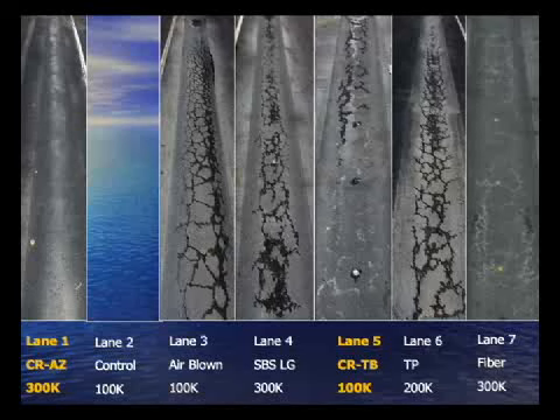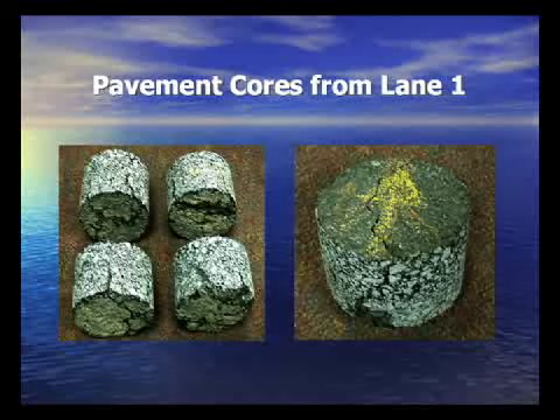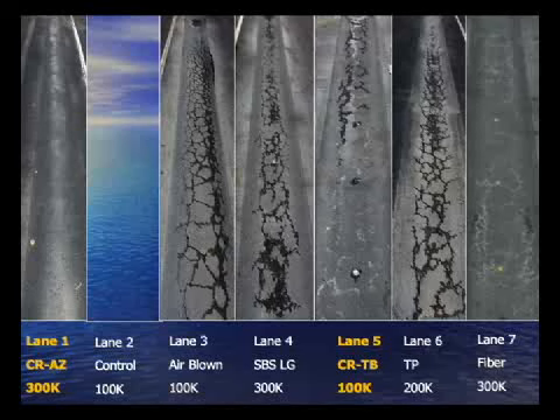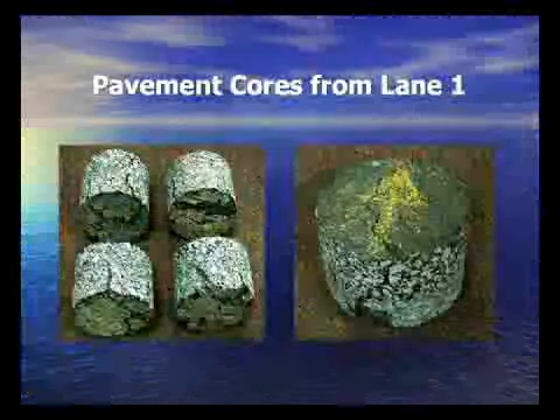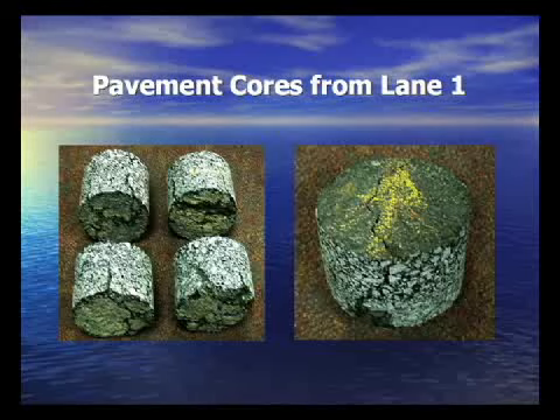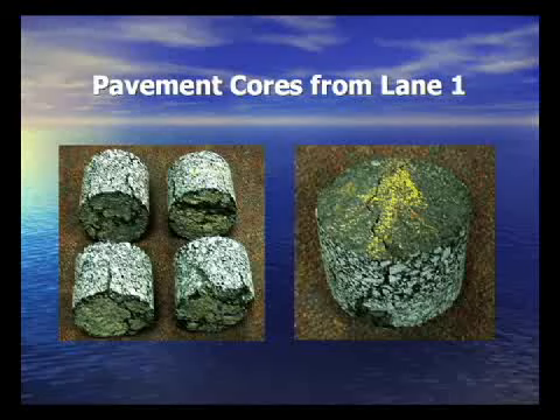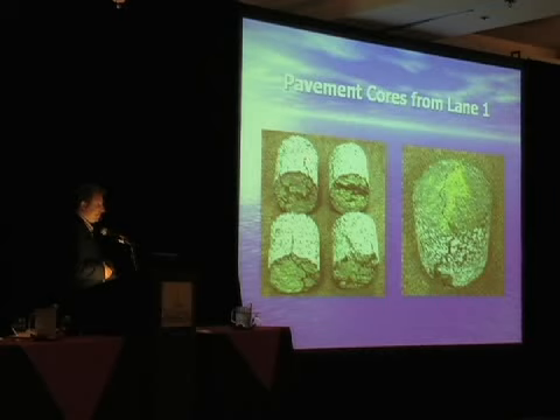This is a visual observation of the rutting. Our ALF technicians do strain, they map the cracks. They do crack mapping. At regular intervals, they go out and they do various rankings that I'll talk about next. But what I wanted to do here was pause and look at the cracking. If you look at lane 1, we don't see any surface cracking. This is the composite section with crumb rubber Arizona over the control, okay? What we see is that there actually was cracking. We've taken some cores, and the cracking started at the bottom of the control mix, went through the 2 inches, reached the boundary at the Arizona wet process, and basically arrested.